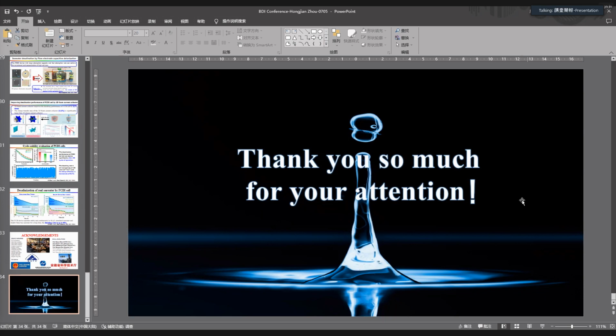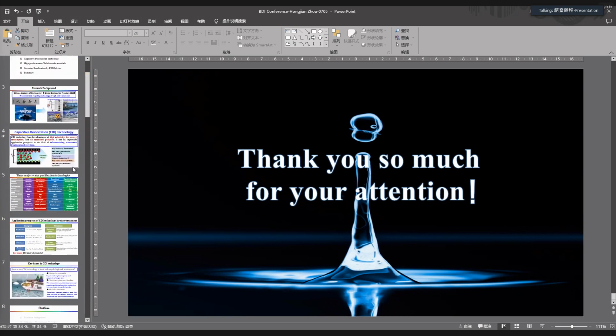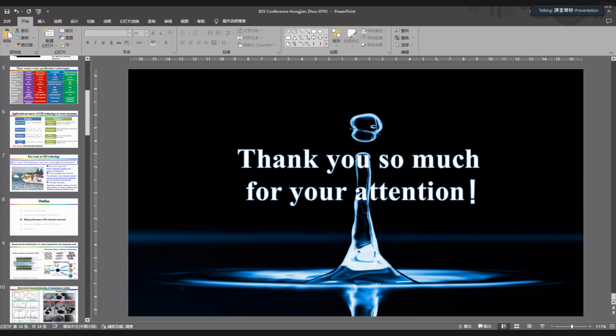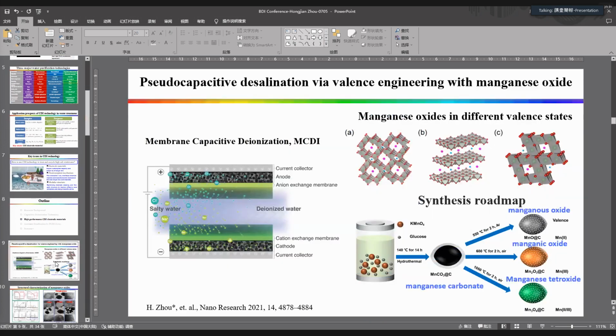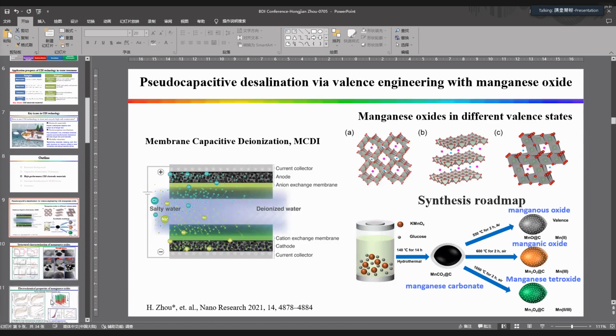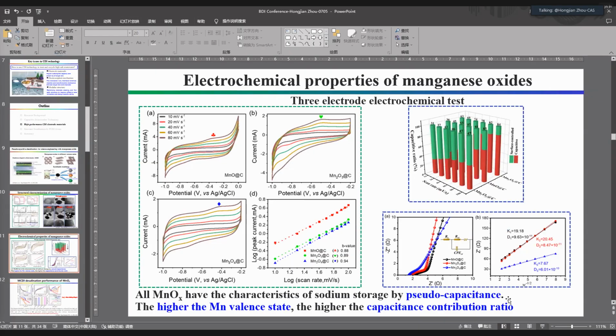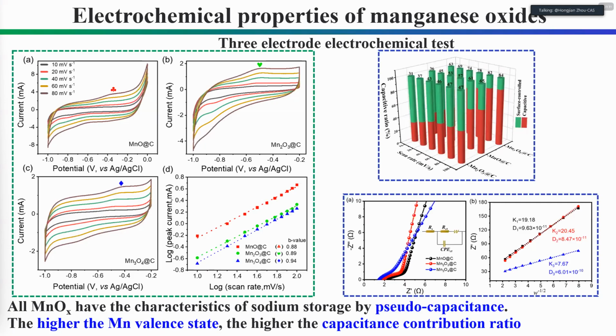Just a clarification question, because in one of the first slides you mentioned that lower valency was more suitable for CDI of the manganese oxides. But what I could see from your data and what you also wrote was that the higher valency provided higher capacity. So can you elaborate how that goes together? Yes, this one, right? Yeah. Yes. We were also curious about the electrochemical property. We find the higher manganese valence state shows a good capacitive contribution ratio. But in the end, in the CDI part, the lower valence state shows good desalination performance. We are still trying to figure out this question, but we couldn't get the answer.